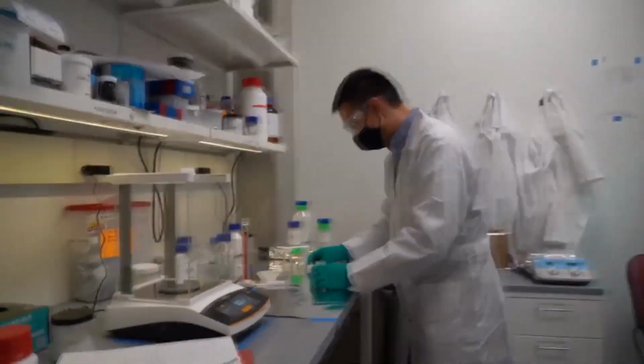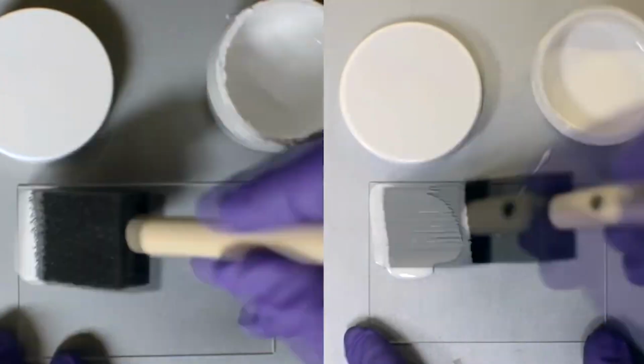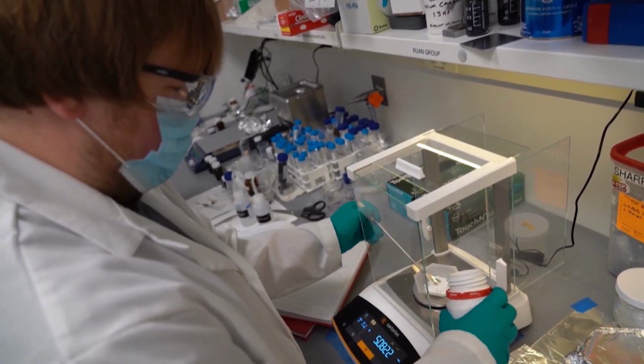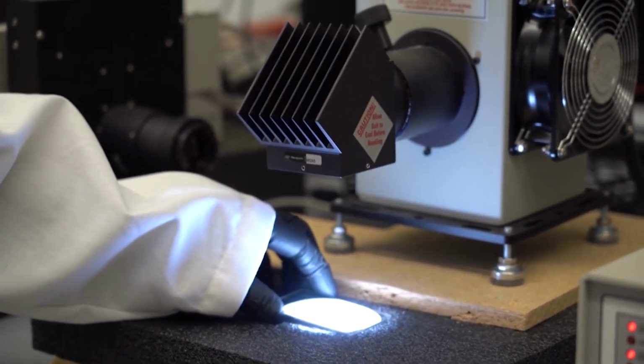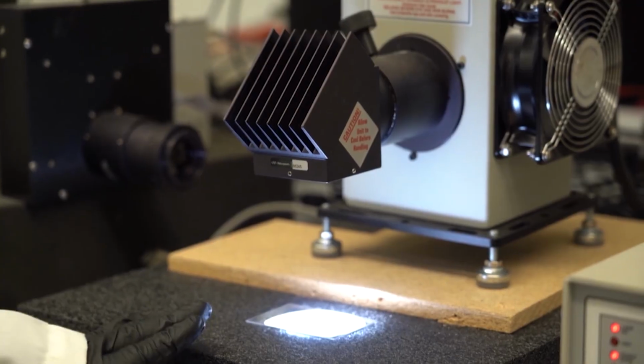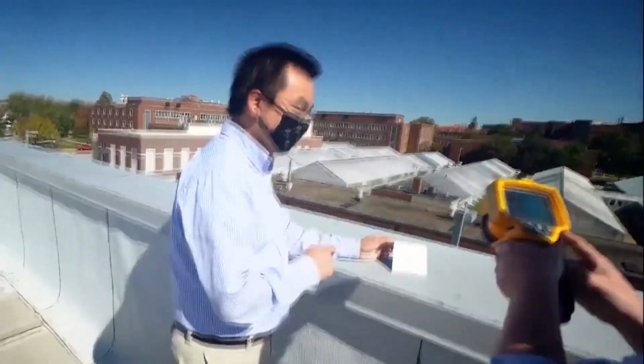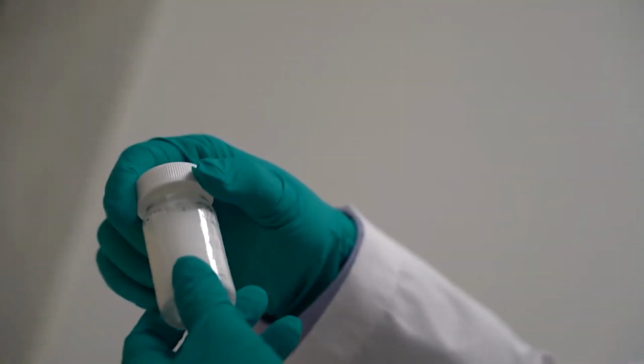It was exactly according to this recipe that, in the year 2021, a team of scientists from Purdue University in the United States created a cooling coating. The paint, named Purdue Ultra White, is made of barium sulfate particles with diameters ranging from 50 nanometers to 2 micrometers. This allows the material to effectively reflect a wide range of solar radiation, in total about 98.1% of incoming sunlight. Moreover, thanks to the selective emission of barium sulfate, 97.7% of the thermal radiation generated by this paint falls within the atmospheric transparency window. As a result, surfaces coated with Purdue Ultra White are 4 to 5 degrees cooler than other white surfaces during the day, and 2 to 4 degrees cooler at night. In other words, thermoradiative materials that provide cooling purely due to their optical properties already exist.